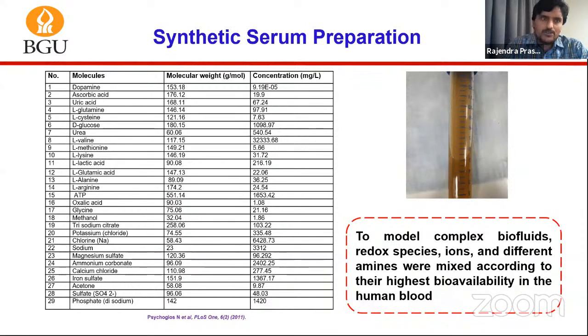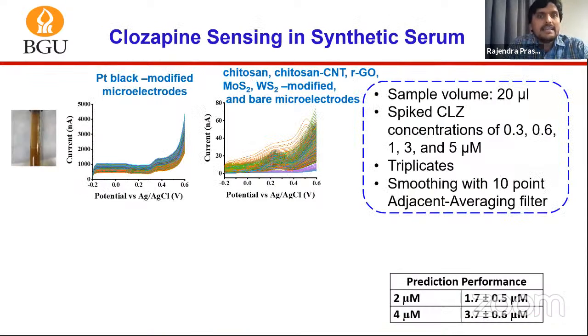So here I will show you the first result, that is synthetic serum. For that we used 29 species, and we mixed them. We prepared a synthetic serum solution, and we spiked clozapine into it in a 20 microliter volume sample, and we recorded the electrochemical data set.